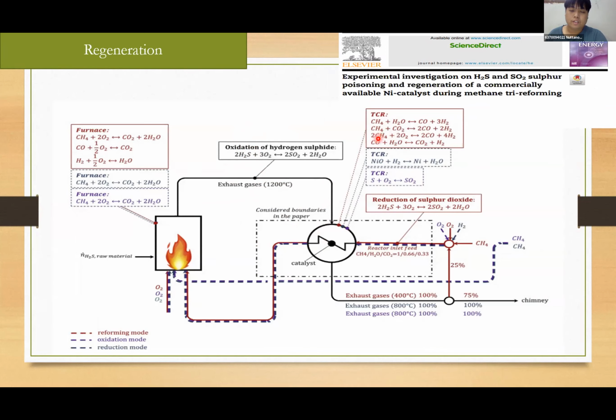Moreover, the reactor consists of 3 reactions: steam reforming, dry reforming, and partial oxidation, which is called tri-reforming. And in this process, there are 2 operation modes: reforming and regeneration. In reforming, the reactants were heated by exhaust gas, which came from the furnace, and some of the exhaust gas was recirculated to the inlet feed to fix the ratio between methane, steam, and carbon dioxide. In regeneration mode, the hydrogen and oxygen were heated by exhaust gas too, but the circulation line was closed, so the exhaust gas was sent to the chimney.